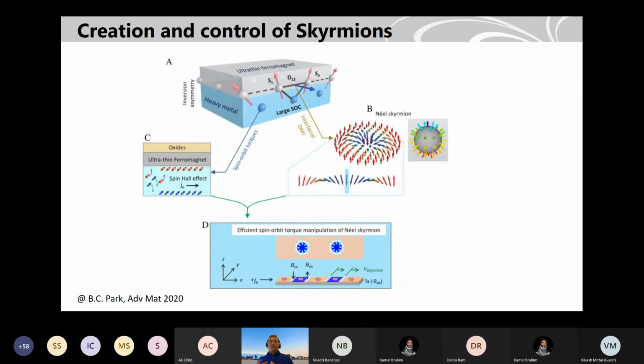And people are trying to also control the magnetic skyrmions. So you can create these skyrmions and you can control them by spin orbit torque. For example, here, this is a review article, you can see that you create these skyrmions, and by using a high spin orbit material, when you pass a current, you actually create spins again, and these spins will be able to change the magnetic configurations of these skyrmions. So you can create and control the skyrmion property by all electrical means.